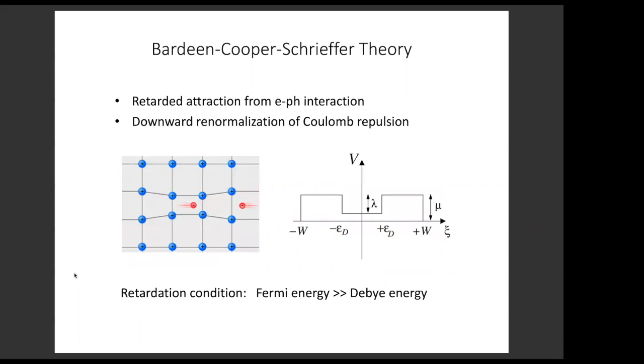As we all know, the Bardeen-Cooper-Schrieffer theory successfully explains superconductivity in conventional metals, and here the attractive interaction between electrons comes from the electron-phonon interaction, and this attraction is limited to low energy within the Debye frequency. On the other hand, there's a much larger direct Coulomb repulsion between electrons. So really, if we look at the interaction as a function of energy, at all energies the interaction is repulsive. It's just that within the Debye frequency, it's less repulsive. And what made it still possible to get a pairing is this crucial retardation effect. Because the Fermi energy is much greater than the Debye energy, there's a large renormalization effect. The Coulomb interaction becomes strongly reduced at low energy.